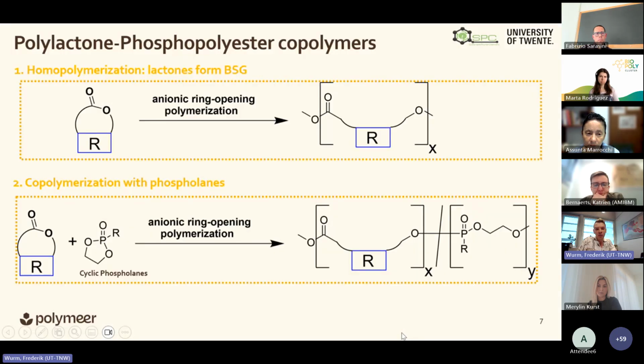And what we are doing, so we take ring opening polymerization of lactones, and so cyclic ester molecules. And the goal is to use also new monomers that Assunta mentioned from the BSG and make homopolymers. But also what my team is an expert in is using these a bit more exotic cyclic phosphoester monomers, because they can act as viable breaking points. Depending on this microstructure around this phosphorus, you can control hydrolysis lifetimes selectively. And then we incorporate just a little bit of those into copolymers of these lactones to trigger environment-specific degradation.